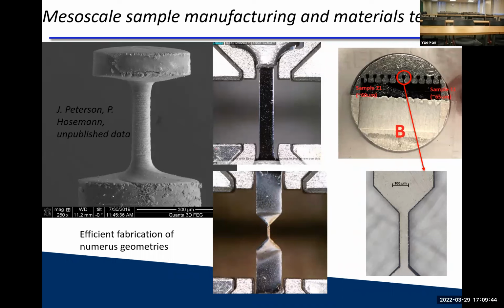Because the way we make those, right, we polish them, the thinnest you can mechanically polish is like 30 microns, give or take. And that's a little bit of a gamble at that point, right? Not every sample is going to be a success. So if you want to be smaller than 30 microns or so, then I would probably do it round, because that way I can guarantee it's always 1-to-1, right?